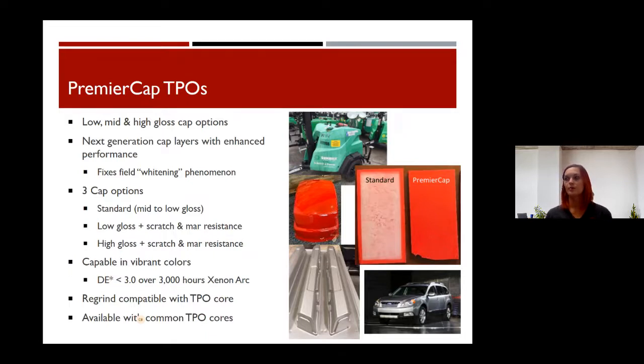So we came up with the Premier cap line, which solves that surface issue. You can see off to the right, we did post-forming weathering on standard, and then on the Premier cap line, and the Premier cap held up. It didn't show that same whitening phenomenon. So that's where it started out, just to solve that issue.